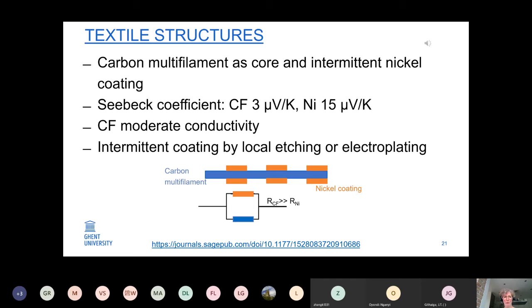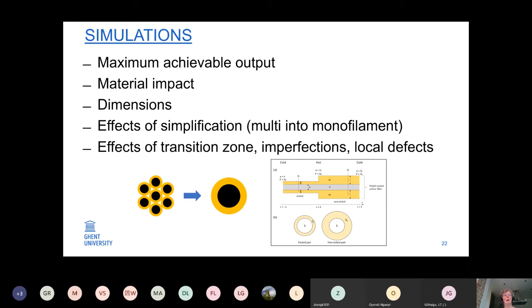How did the models help us here? Well, first, on a material level, just give us an idea on the maximum achievable output, the material impact, both considering the conductivity of the materials as well as their Seebeck coefficients, the dimensions of the whole system, and then for the modeling, we needed to do some simplification, but we also managed to show that the simplification of the multi-filament into a monofilament with the same cross-sectional area of the carbon fiber and the nickel coating is allowed. It doesn't have an impact as long as a good contact can be guaranteed.